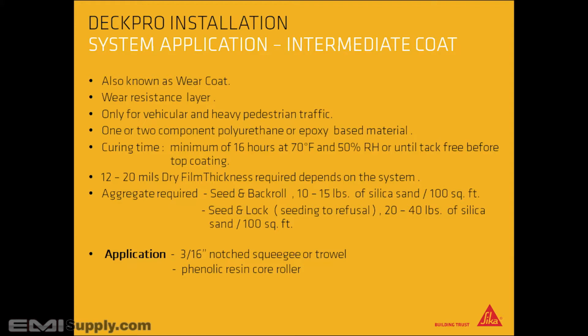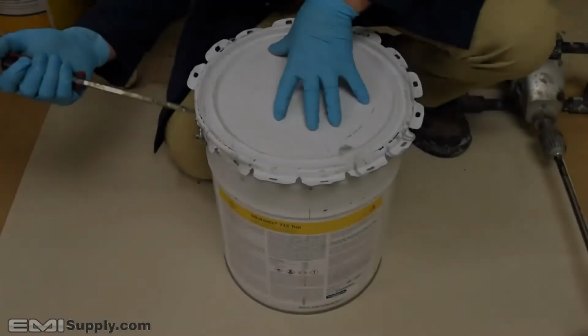Aggregate required for seed and back roll is 10 to 15 pounds of silica sand per 100 square feet. For seed and lock, also seed to refusal, 20 to 40 pounds of silica sand per 100 square feet is required. Apply top coat using a 3/16 of an inch notched squeegee or trowel and a phenolic resin core roller.